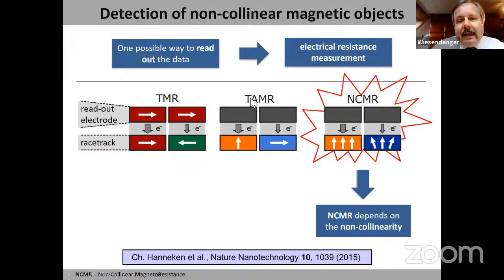You all know about the tunneling anisotropic magnetoresistance effect, which allows us, even with a non-magnetic top layer, to distinguish between magnetic layers with an out-of-plane anisotropy and an in-plane anisotropy, because due to spin-orbit coupling effects in the band structure, there is a modification in the local density of states to which you are sensitive with the tunneling effect, and so you can indeed distinguish between out-of-plane and in-plane magnetized layers in this way, which we also actually did 15 years back in time based on STM.